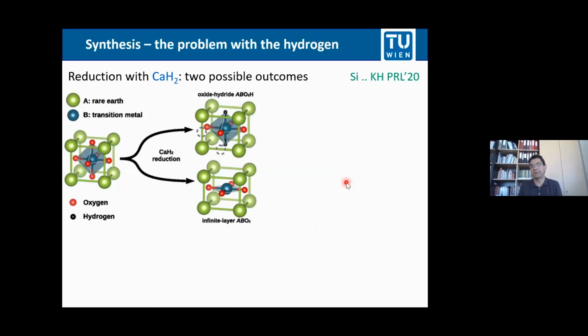more complicated in experiment, because this reduction with calcium hydride might result in different end products. So that's a perovskite to start with, say lanthanum nickel O3, and you want to have this infinite layer structure, but instead you could also have a topotactic hydrogen where before the oxygen was. That has been observed in early transition metal oxides before, actually even in nickelate. So there are some experiments showing that you have some lanthanum nickel O 2 point something hydrogen something. So these systems can occur.